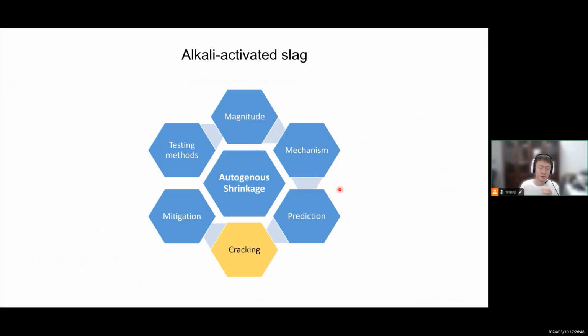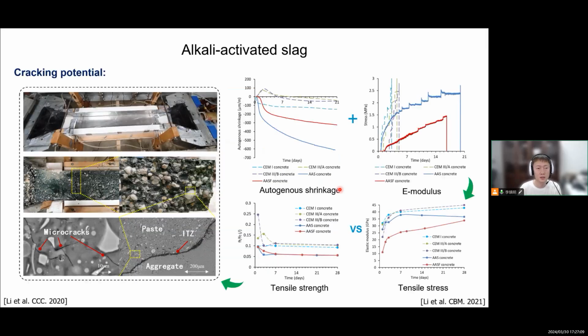And since we can predict the free shrinkage, we are also curious about the cracking when the material is in restrained condition. For example, there is old concrete, there are adjacent structures. Nothing in our house is actually free. Everything is connected with each other. So there can be tensile stress and cracking potential. So we need to study that. I studied the concrete for the cracking potential by this TSTM and also the ring test to restrain the concrete and then to observe the cracking on the macro scale and also on the micro scale. Basically, the methodology is like we know the free shrinkage and then we know the elastic modulus.